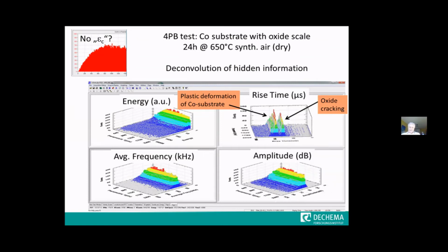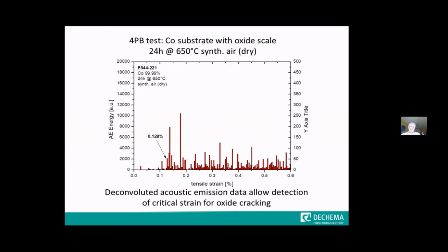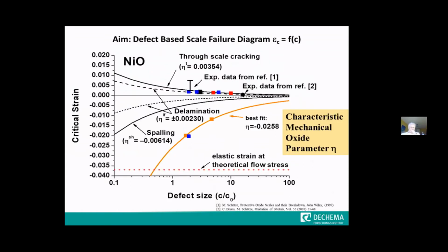Oops, again, the wrong one. And this would then lead to results as shown here. For instance, indeed, now we can see, and this is again for tensile strain now, at the beginning not much is happening, and then suddenly the acoustic emission activity starts to increase significantly, and by that you can determine a critical strain for the failure of these oxides.